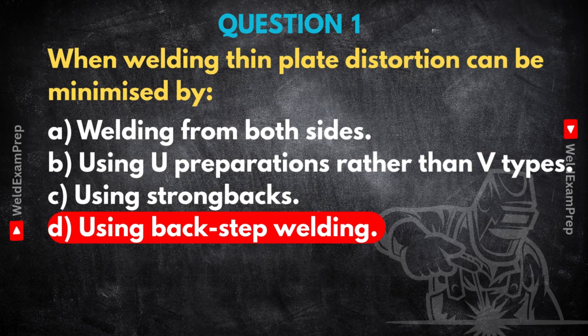And the reason this is so effective is it helps spread the heat input out much more evenly. You're not getting that continuous linear buildup. Instead, you're constantly shifting where the maximum heat is concentrated. This really cuts down on the total heat buildup at any one spot. And that's crucial for stopping too much shrinkage, which is the main driver of distortion in thin plates. It's all about managing that cooling. So it's not just less heat, it's about strategically managing the cooling, breaking up that thermal wave that pulls things out of shape.